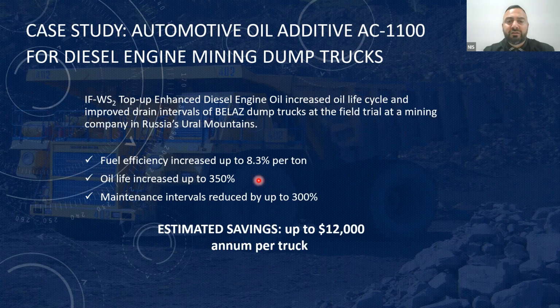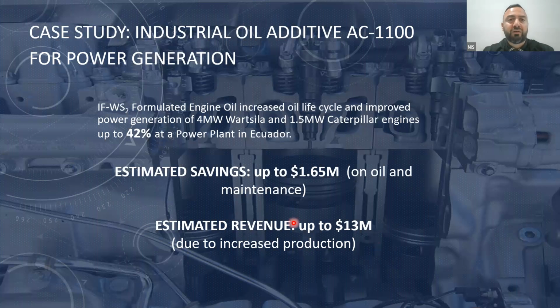For dump trucks, there are several results that we have with some of our customers in East Europe. So we see that fuel efficiency increased, that's what they're reporting, up to 8.3% per ton of the material. Oil life increased up to 350%. So their wheels are spinning, they're making more money, they don't stop as often to change the oil or filters and so on. And maintenance interval reduced by up to 300%. So they estimated savings per truck of around $12,000 a year. Again, they're their numbers. We don't challenge the numbers from our customers usually.